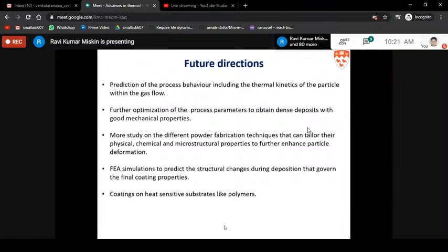And then FEA simulations are being extensively carried out because one remaining problem is that we are not able to retain all the ceramic particles when we spray. For example, I could retain only 23% out of 50, which is around 46%. So the efficiency is around 46% only. They're trying to simulate these conditions to see what we can do to potentially improve the ceramic retention.